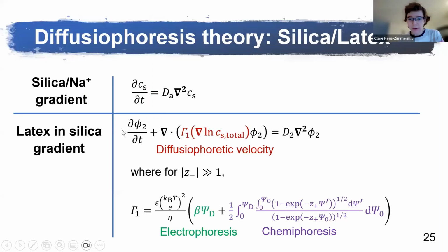For the latex, the equation looks a little more complicated. On the left-hand side, we first have the rate of change of the volume fraction of latex with respect to time. On the right-hand side, we still have a diffusion term. Here, D2 is the diffusion coefficient of the latex particles, and these particles are relatively large, and so we could ignore this diffusion term.